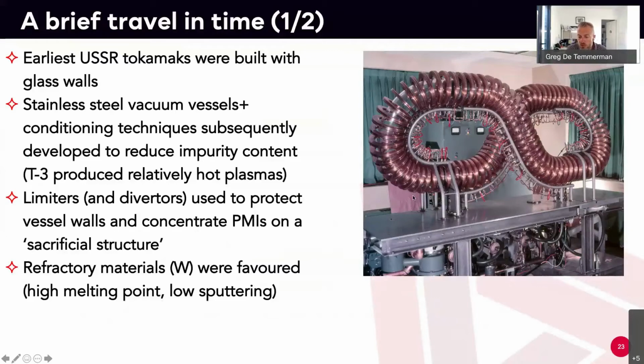Now, pretty quickly, people realized that glass was really bad because it's electrically insulating and you have a plasma inside, and you actually need a conducting surface for stabilization. Insulators don't work too well when you have a plasma, you tend to have arcing and so on. So people moved quickly to stainless steel. Stainless steel is very good, but you always have hydrogen inside steel. And that was an issue because you were basically degassing the steel inside the plasma. I should have said that we work in vacuum, in really high vacuum actually, when we make a plasma. So we have to have very clean surfaces, and stainless steel at that time was not ideal.